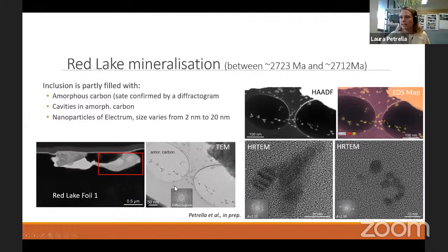You can see that this inclusion is filled with amorphous material. There's no atomic arrangement in this phase, so it is definitely amorphous, and it contains several nanoparticles that are easily seen here. This is an element map of the inclusion, and you can see that the amorphous material is made of carbon, and the nanoparticles are made of silver and gold.